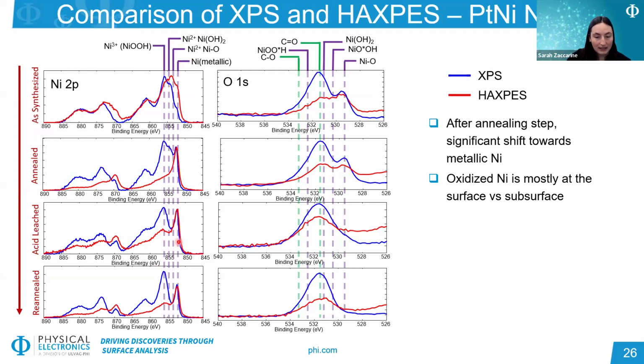So this is suggesting, again, that the nickel towards the surface detected with XPS is highly oxidized, but with the HAXPES beam, we're detecting more into that bulk nickel metal core.